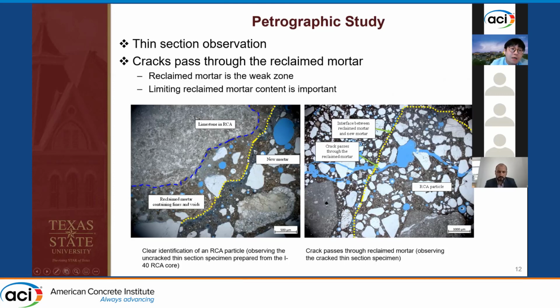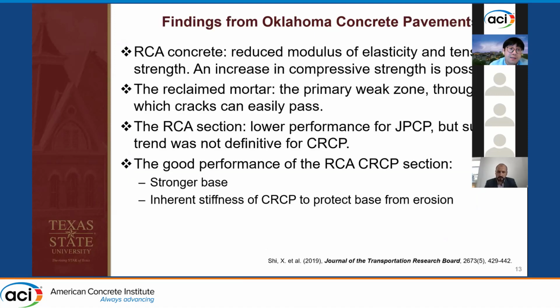Then we also introduced some cracking in the core we took from the field. Then we found the cracking actually passed through the reclaimed mortar. So we can conclude that the reclaimed mortar is a weak zone in this system. So there are some key findings from Oklahoma concrete pavements.